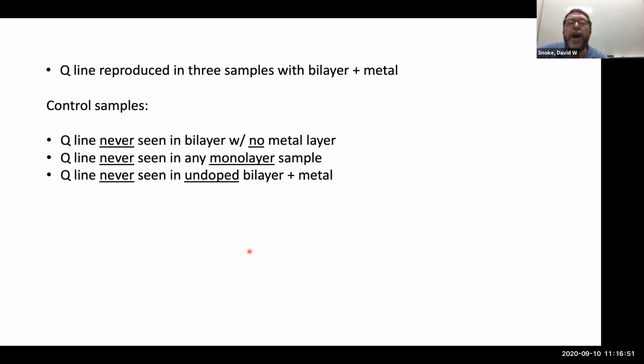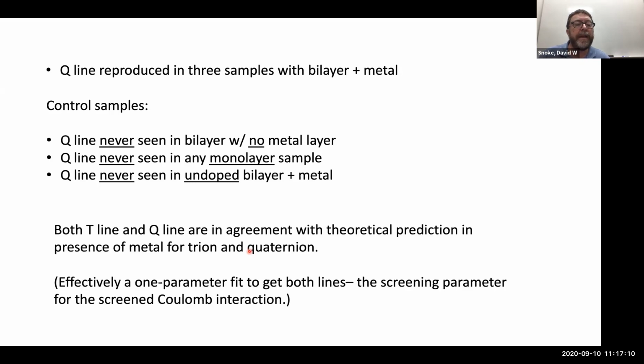And if we make an undoped bilayer with a metal, we don't see it, okay? Nor do we see the trion in that case, because both of these need to pick up extra charge in order to exist. So without doping, you don't expect to see either of those. So the control samples all work as expected. As I said, the energies agree with the theoretical predictions, given that we have 1 parameter that we can vary, but we have to fit both lines with that essentially 1 parameter.